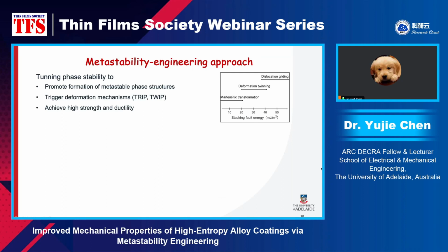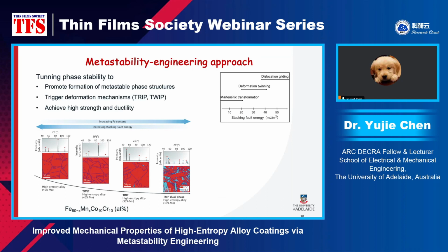The metastability engineering approach is not something new. It has already been widely used in high manganese steel and titanium alloy to promote strain-induced phase transformation. High-entropy alloys are very suitable for applying metastability engineering, since the high-entropy alloy concept widens the alloy design window for tailoring phase stability, stacking fault energy, and also the associated deformation mechanism. Therefore, the metastability engineering approach has been successfully applied to several high-entropy alloy systems. For example, this is the most famous one: this iron, manganese, cobalt, chromium metastable high-entropy alloy.